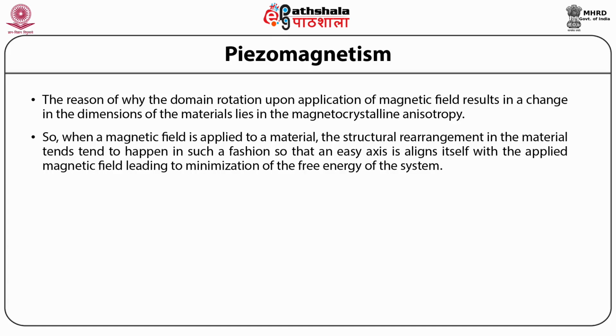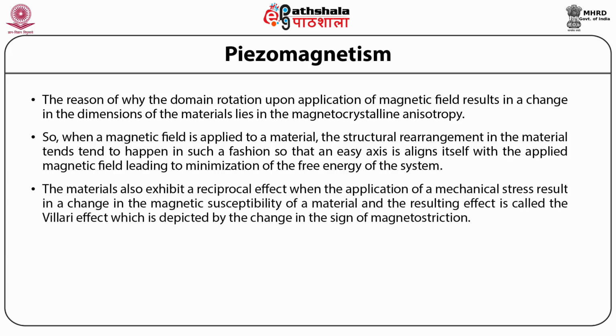As a result, the strain is generated in the materials as different crystallographic directions have different lengths and magnitudes. The materials also exhibit a reciprocal effect when the application of a mechanical stress results in a change in the magnetic susceptibility of a material, and the resulting effect is called the Villari effect, which is depicted by the change in the sign of magnetostriction. For example, in iron, it changes the sign from positive to negative when iron is subjected to a field strength of 40,000 ampere per meter.